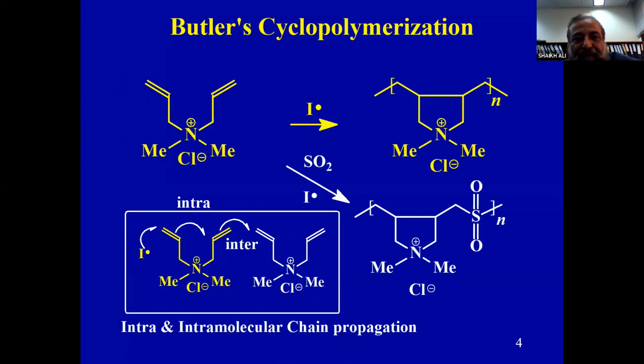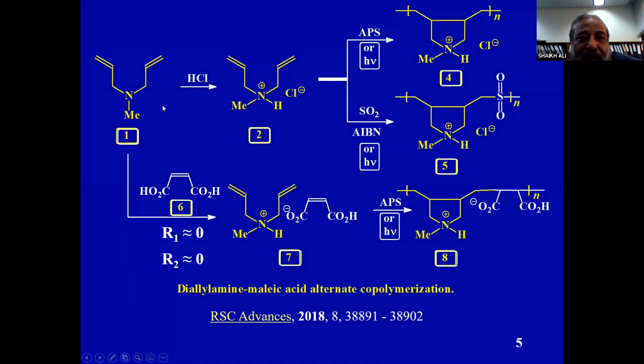Now, you see, we are talking about Butler cyclopolymerization. What is Butler cyclopolymerization? Here a diallyl ammonium salt can go to a cyclic polymer, or with sulfur dioxide it can go to an alternate cyclopolymer. That means this ring and the sulfur dioxide alternate. It cannot add on to itself. They proceed by intra- and intermolecular chain propagation. So you have a homopolymer, and you have an alternate copolymer. Now, here we have a diallyl amine salt. I can make a homopolymer, or with maleic acid, it can give us an alternate copolymer, again alternating like sulfur dioxide.